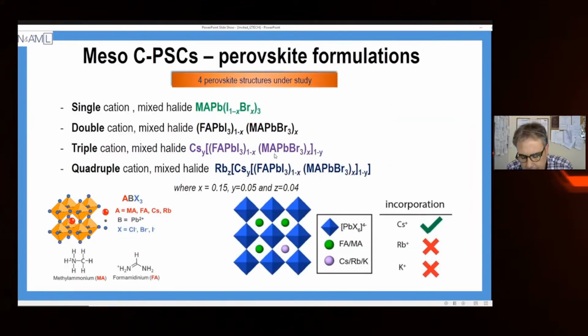Of course, the use of methylammonium lead iodide is not the only option. This is the case where we are talking about a single cation: methylammonium lead iodide, or a mixture of some halides. There is also the case of a double cation, which is a mixture of formamidinium iodide and methylammonium iodide, whose structure is here. And finally, we have the triple cation with the presence of cesium, which, I would say, can generally be incorporated in the crystal structure of perovskite. But in the quadruple cation case, with the presence also of rubidium, it is only to protect the structure, and it is not incorporated into the structure of the perovskite itself.